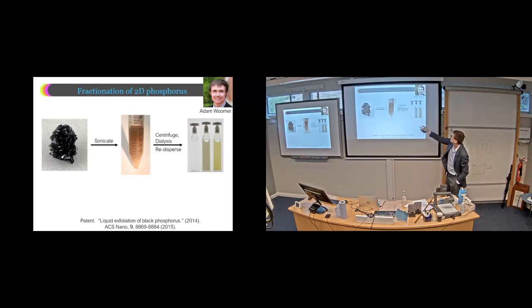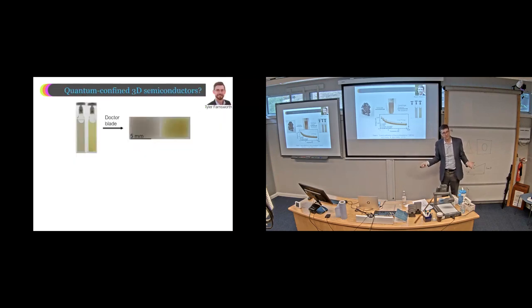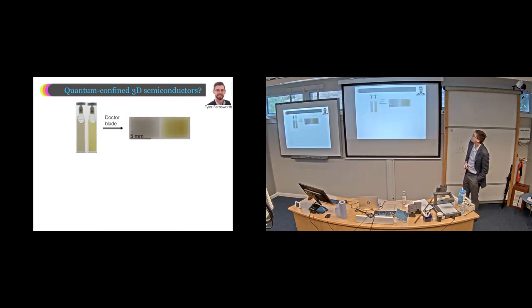That was a pretty cool prediction, but nobody had ever experimentally verified it. So we went to try this by doing a process called liquid exfoliation, where we take the material and we simply sonicate it. It produces this red dispersion. So that red dispersion clearly indicates that something has happened because it is no longer black. We can then centrifuge that to get the thin flakes separated from the thick flakes. So that produces either the thin flakes that are yellow or the thicker flakes that are brown. So we did a whole series of thicknesses and we were able to map out how the band gap of the material changes as a function of thickness. And indeed, we found that by the time that you get to a bilayer, the band gap is 1.8 eV. By the time that you get to a monolayer, it's probably closer to 2.2 eV.